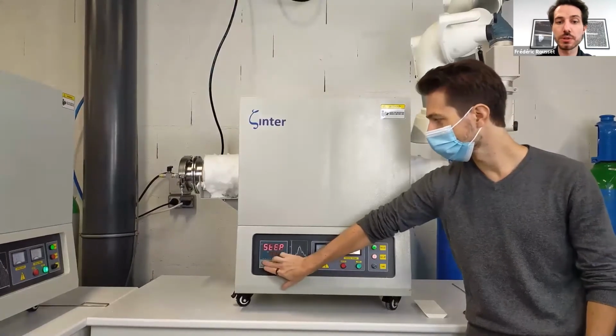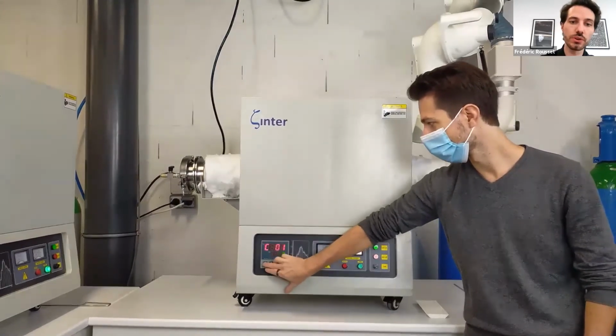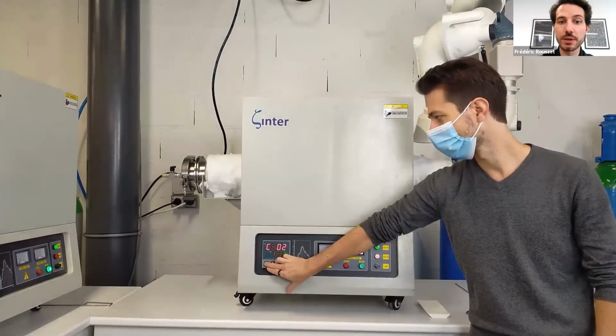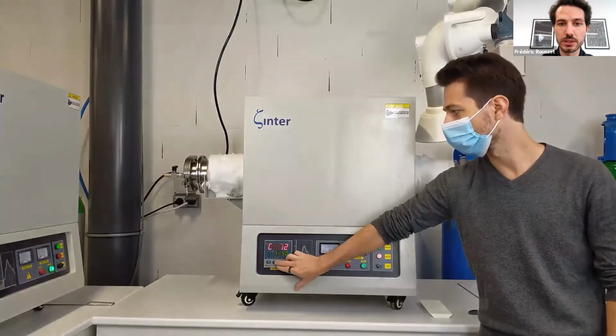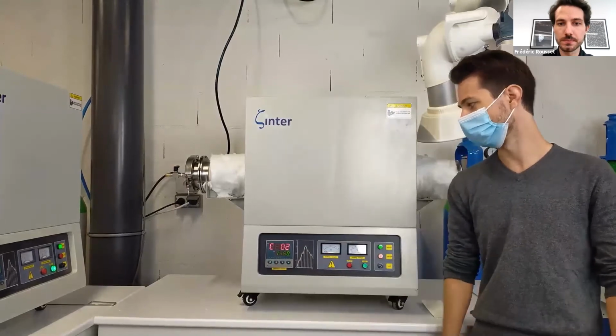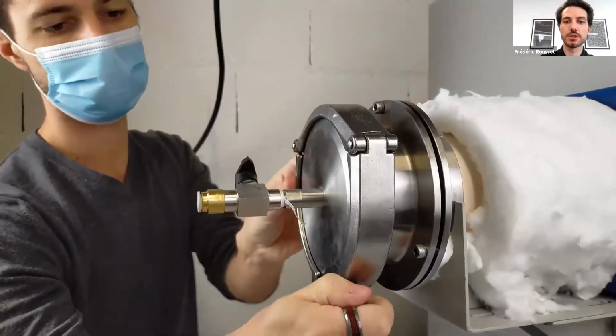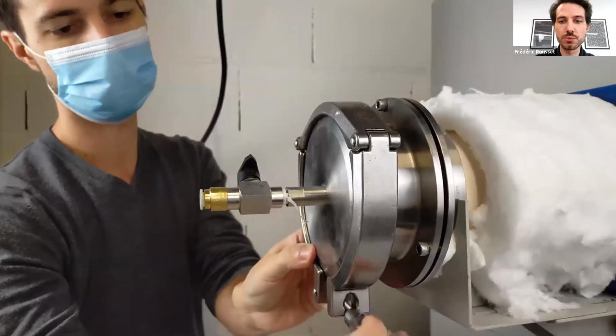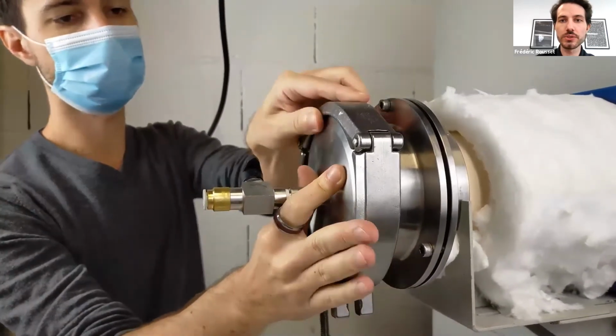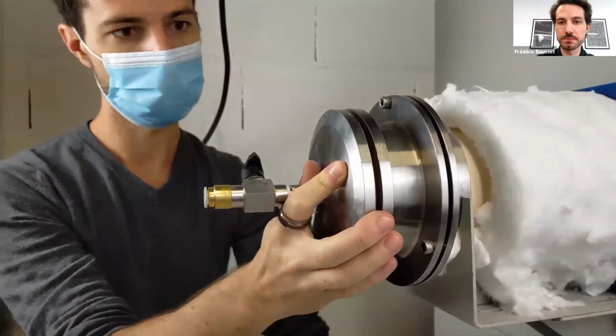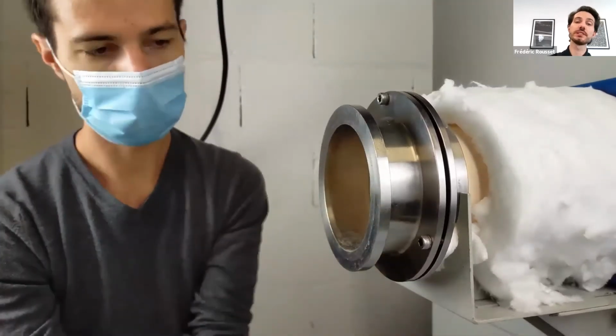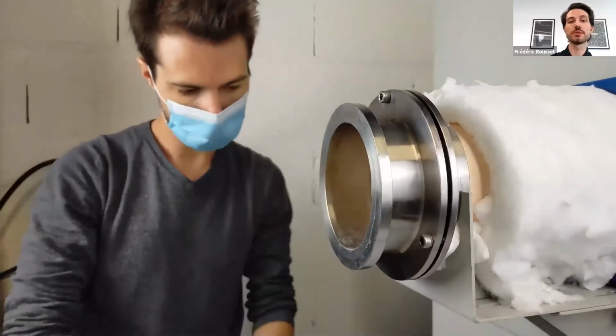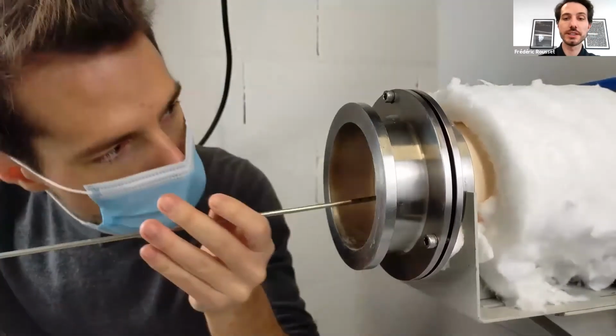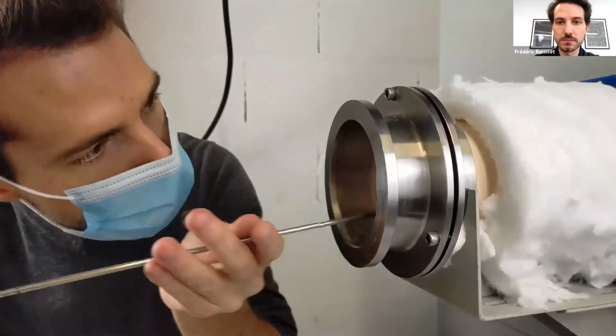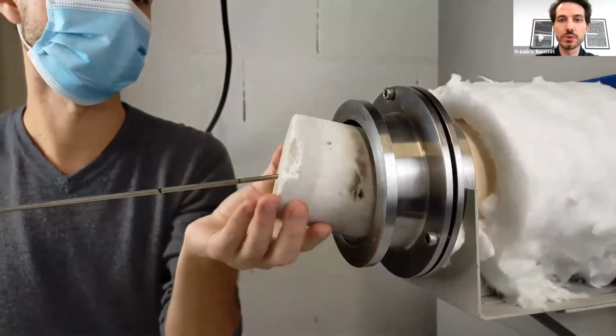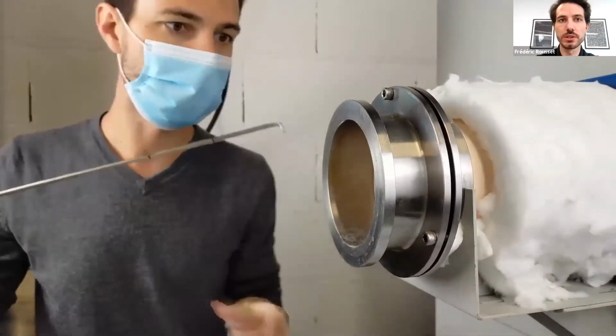I'm going to set the cycle temperature. Those are the cycles that we are giving out also, of course. A little time lapse, and that is where you can take your part out after a couple of days of sintering. Depending on whether it is ceramic or metallic parts, you have to do the debinding or the sintering in the furnace. I'm going to take out the thermal shields and, of course, the part that you have.